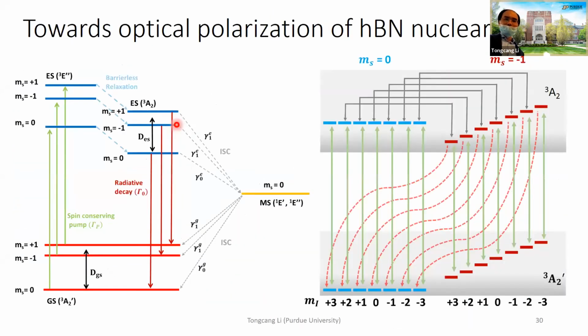So you can think of a spin-1 system, but with three nuclear spins there are 27 states. If you classify them by the sum of the z components of the nuclear spin, you have 7 components, from +3 to -3. Then we use a green laser to excite it. With a level anti-crossing, if the excited state spin 0 and -1 have the same energy, then they can mix. The electron spin and nuclear spin can flip-flop, so they couple. For example, an initial -3 state goes up, mixes and becomes -2, then decays back. After a few cycles, in principle, you can polarize to the +3 nuclear spin state, ideally.